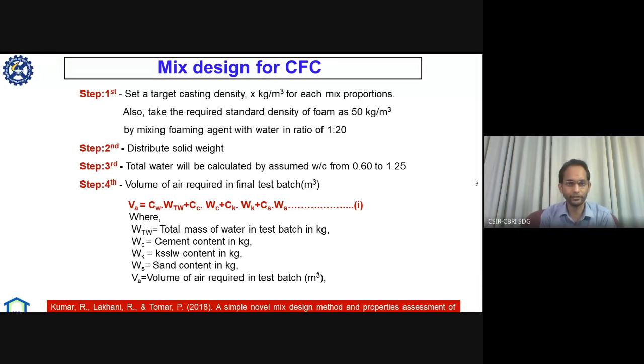Then we have distributed solid weight. What solids have we taken? OPC we have taken. We have taken stone slurry, that is Kota stone slurry. You can call it low grade limestone slurry because it contains a lesser amount of calcium carbonate, and it also contains a higher amount of silicon dioxide. Normally limestone contains approximately 2 to 3% of SiO2, but here low grade limestone or Kota stone contains about 35 to 40% of silicon dioxide. So that's why I am calling this limestone low grade limestone.